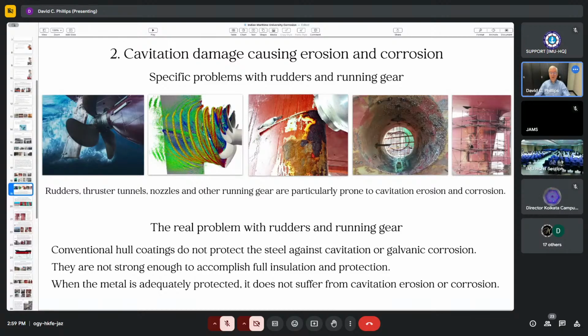Here's your damage. Very often a ship like that has to come into dry dock, and they sometimes have to take the rudder off completely, but at least they have to do welding on the surface to repair it, patch it up. It gets holes in it. It's quite a nuisance. It's quite a headache to many kinds of ships. These rudders are of large container ships, which tend to suffer the most. They have high speeds, they have fast, big propellers, and they have big rudders, and this is what happens.